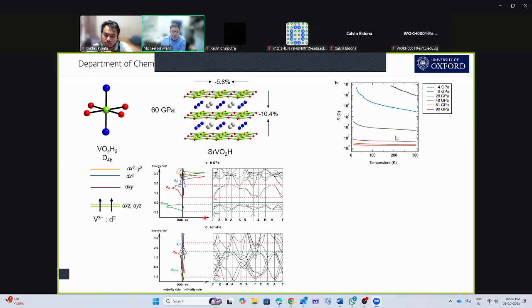If I put this in a diamond anvil cell and start applying greater and greater pressures, what I'm plotting out here is the resistance against temperature, and we see the resistance comes down and the temperature dependence changes from semiconducting to metallic as we apply high pressure. At 60 GPa, what we've done to the structure is compress the V-H-V direction by about 10% and the V-O-V direction by about 6%. We've really crushed the structure, and that closes the band gap and makes the system metallic.